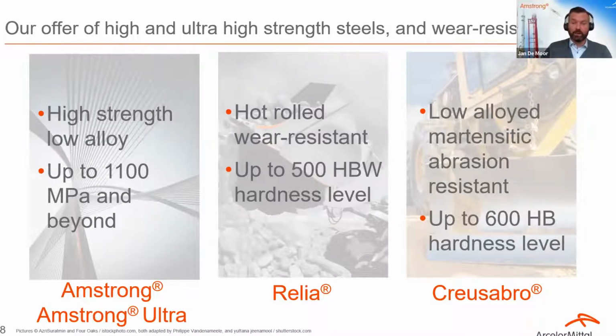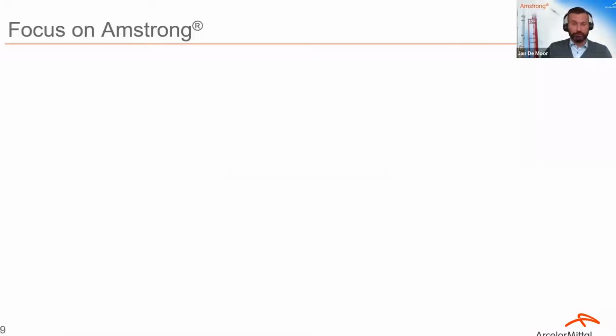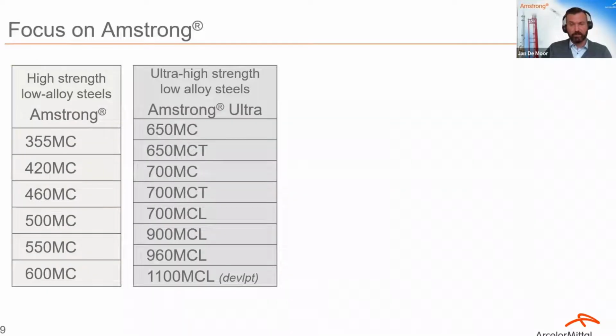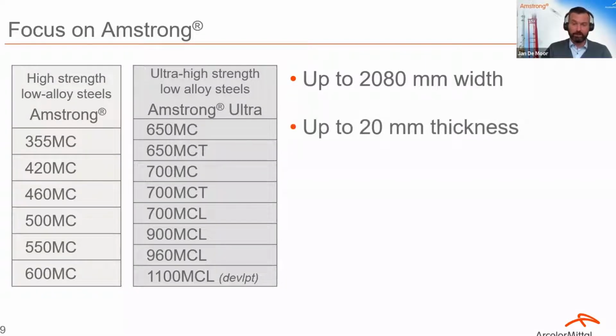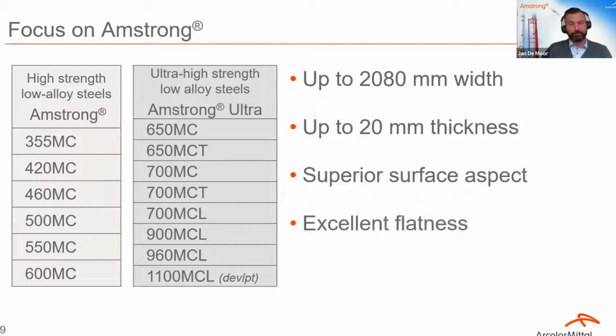Looking at our Armstrong and Armstrong Ultra high-strength steel portfolio, our current range goes from 355 yield strength up to 960 megapascals yield strength, with the 1100 range currently in development. Dimensionally, we can offer up to a thickness of 20 millimeters with a width of 2080 millimeters, available with superior surface aspect, excellent flatness, and minimal residual stresses.